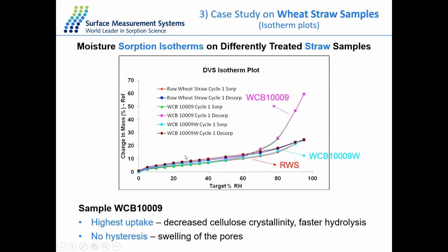And from the mass plot, we can generate the isotherm for 3 different samples as well. So from this comparison in the isotherm, you can see the 3 samples have very similar behavior up to 50% RH, but there are some significant differences in the higher humidity range. So the treated sample, which is the pink one like this one, has the highest uptake, around 60% change in the mass at 90% humidity.